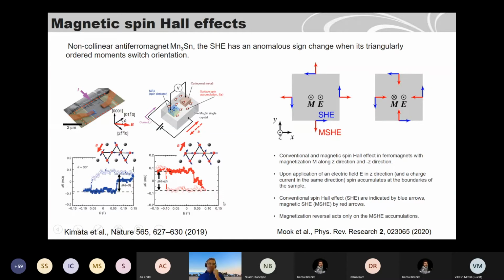So this effect was not known before, but it has been discovered now. They could see that when you switch the magnetization with the magnetic field from this direction to the other direction, you see a change in the resistance, which also reverses sign. That gives rise to what is called the magnetic spin Hall effect. And many people, as I know, are working on antiferromagnets. If you find a non-collinear antiferromagnet, it should show such behavior.